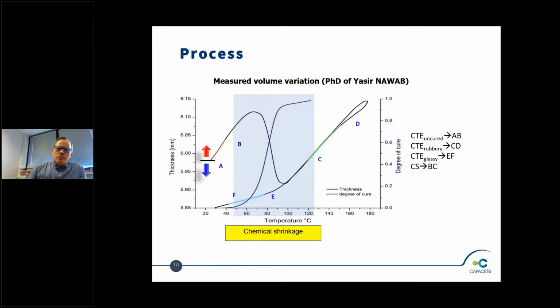So what I want to prove with this slide is that we have to really know the behavior of the material well, and not only know the behavior, but be able to characterize it, to put some numbers on it so that the industry can model the process and obtain the residual stress state on the specimen. Because for very demanding applications like aerospace, all this is modeled in finite element modeling in order to know if the specimen, if the blade for example, contains a lot of residual stresses which may affect its behavior. Then you have chemical shrinkage, and we have to live with this physics in the material.